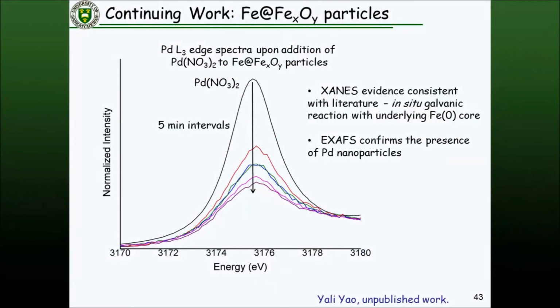And sure enough, we take those iron oxide particles, the palladium L-edge spectra, time 0, we have a 4d8 system. Within 5 minutes, that palladium is fully reduced on the surface of the iron oxide particles as palladium 0. And EXAFS actually shows that these are palladium clusters of about 1 to 1.5 nanometers in diameter.